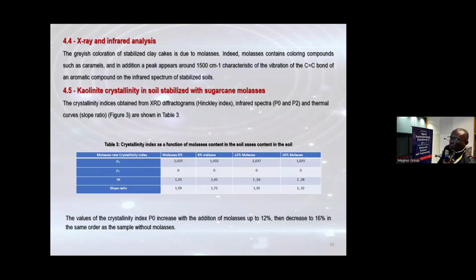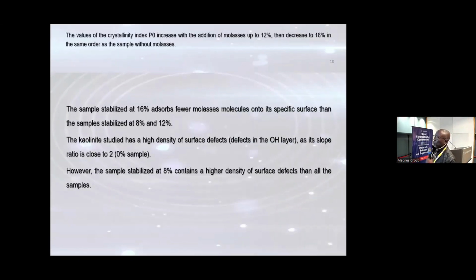The crystallinity index obtained from X-ray diffractogram, infrared spectrum, P0 and P2, and thermal curves slope ratio is shown in figure 3 and table 3. This is the value found. The value of crystallinity index P0 increased with the addition of molasses up to 12%. That decreased to 16% in the same order as the sample without molasses.